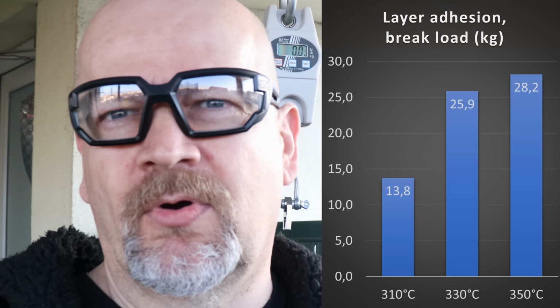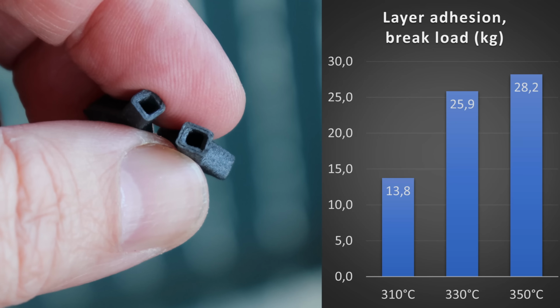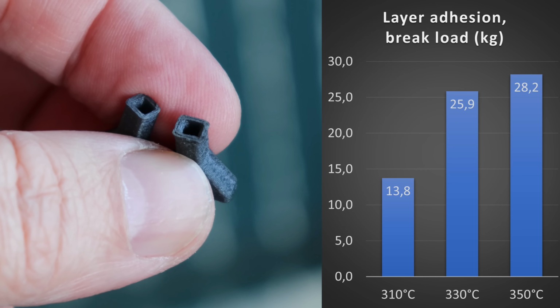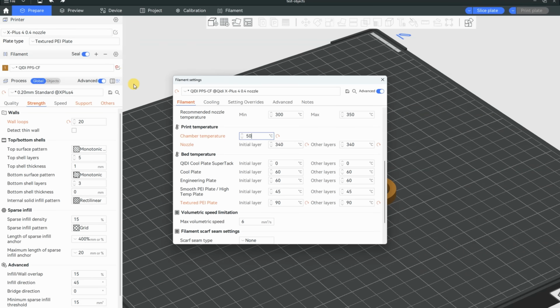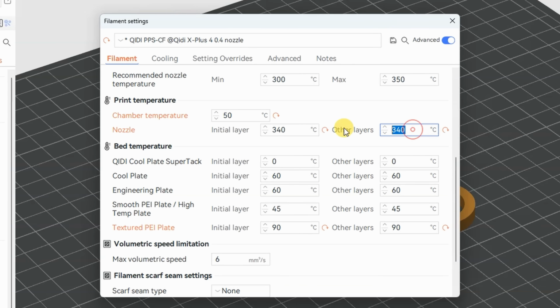Definitely you don't want to print this at 300 degrees Celsius, which is the max for many printers. As I mentioned, these are printed with 2 walls and 0 infill. And I decided to print everything at 340 degrees Celsius. Here you can see my settings.